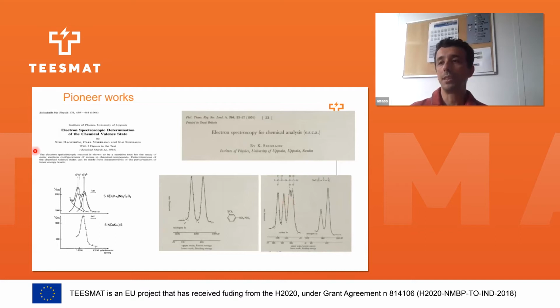And this is the first paper, the pioneer work, where they proved that, for example, for sulfate-based material, depending on the oxidation state of the sulfur, like for example here, the most reduced sulfur, sulfur 2-, or elementary sulfur or oxidized sulfur, we can see clear displacement or chemical shift depending on the oxidation state of the sulfur. And afterward, Siegbahn proposed other analysis for polymer materials, and depending on the chemical structure of the polymer, we can have different signatures when we probe the carbon or oxygen related core level. That is just some historical background.